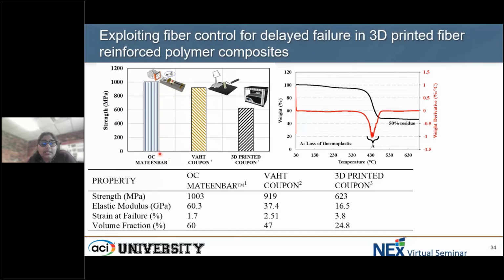It's a highly cumbersome kind of technology already, but to have to align those fiber orientations in order to get that resulting cross section is very challenging, and it won't be that controlled at this point. With the high mechanical deviations, we will basically go back to the same problems of fiber hybrid composites. If you look at a vacuum assisted hand layup technique, VAHT coupon, that is produced using a manual technique of combining layers with a matrix component and completely wetting out these fiber layers.